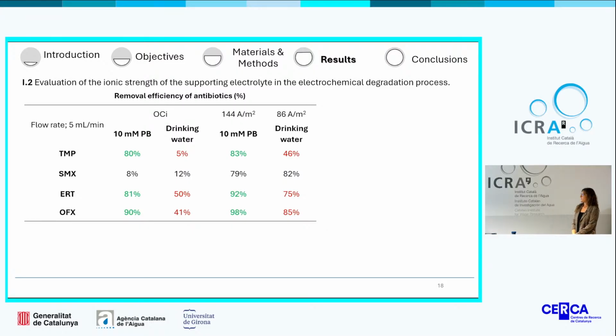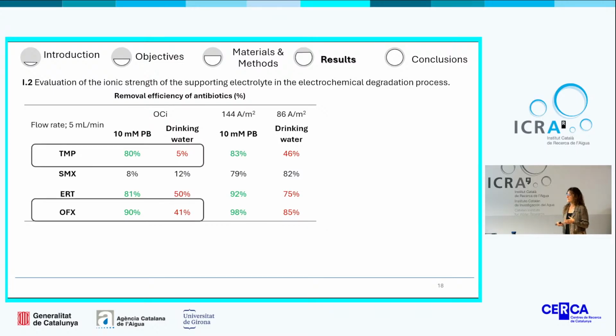The evaluation of the ionic strength of the supporting electrolyte was also performed using the same experiments, but changing the background electrolyte from 10 millimolar phosphate buffer to drinking water. According to the result, we could observe that in the case of trimethoprim and ofloxacin, which are highly absorbed onto the sponge, in drinking water they were clearly affected.